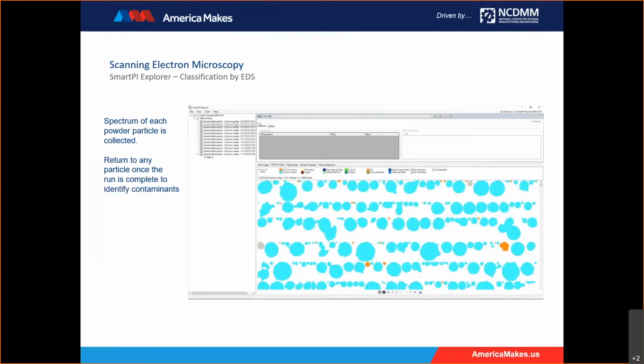So in this data set, we can see that most of the particles are the cyan color, and those are the aluminum, silicon, tin, magnesium powders that we expect. But we have a few orange ones that have been identified as aluminum oxide. And after reviewing this data, we can even return to individual particles if the powder stub is still in the tool to confirm the classification or perform additional characterization. And this may be useful if you want to investigate the few gray colored particles that are currently unclassified.